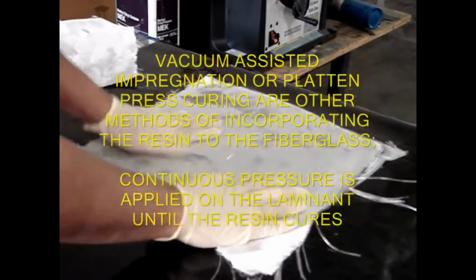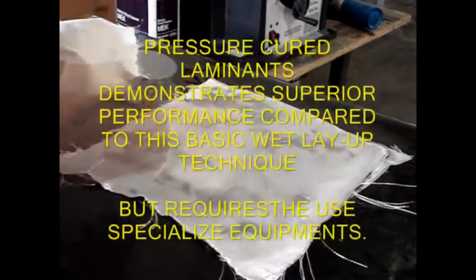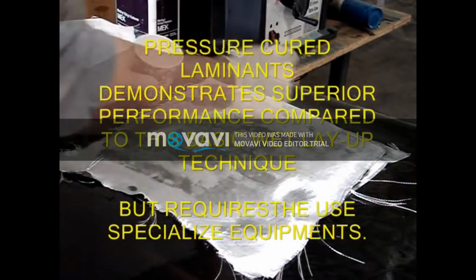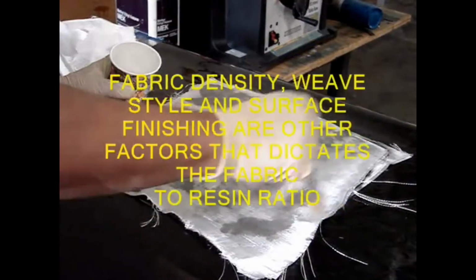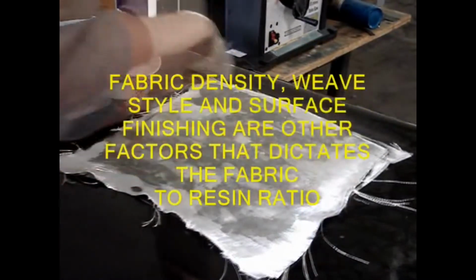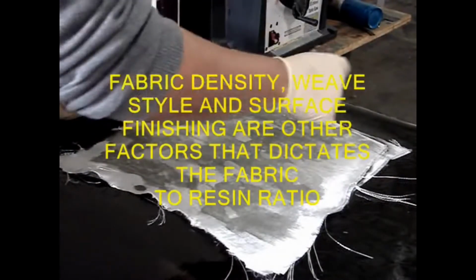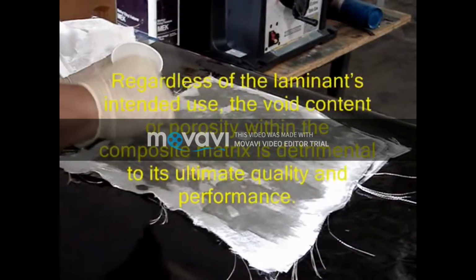Continuous pressure is applied on the laminate until the resin is cured. Pressure cured laminates demonstrate superior performance compared to this basic wet layup technique, but it requires the use of specialized equipment. Fabric density, weave style, and surface finishing are other factors that dictate the fabric to resin ratio.